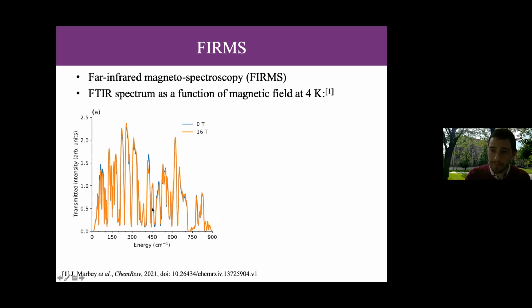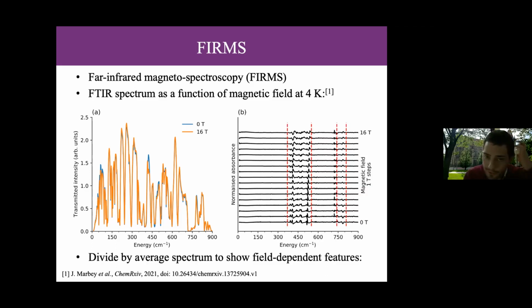And so you can see here the 2 different spectra at the smallest and largest field, so 16 Tesla, are pretty similar. There's not much differing between them, but little shoulders of change and little shifts happen, okay? Which means something is changing. So if you then calculate the average spectrum across all fields, and then divide each field spectrum by the average, you get this picture here.